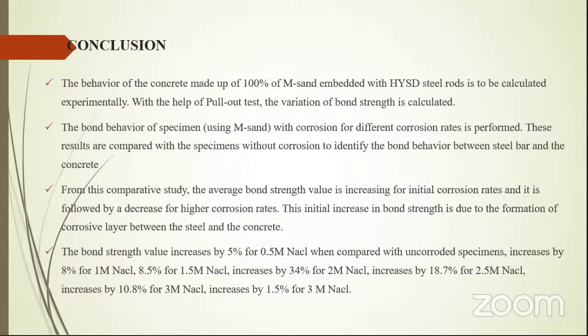Conclusion. The behavior of concrete made up of 100% M sand embedded with high yield strength deformed steel rods is to be calculated experimentally. With the help of the pull-out test, the variation of bond strength is calculated. The bond behavior of specimens using M sand with corrosion for different corrosion rates is performed. These results are compared with the specimens without corrosion to identify the bond behavior between steel bar and the concrete.